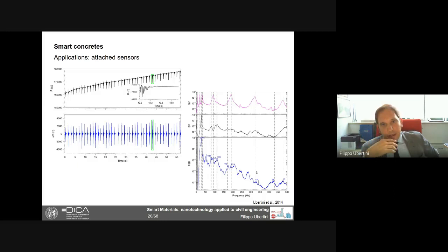If you apply a high-pass filter above 5 hertz, you get the blue signal. So you get no mean, you remove the polarization, but of course you are blind to the first 5 hertz of the spectrum. But then if you compare the power spectral density of the blue signal in the bottom right image with the singular values of the accelerometers attached onto the beam, with purple the lateral accelerometers and with black line the vertical accelerometers, you see that all vertical peaks that are present in the singular value plot of the accelerometers are also present in the power spectrum of the smart sensor, the cement-based sensors with nanotubes.